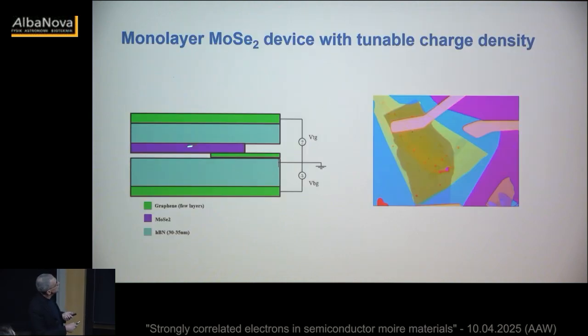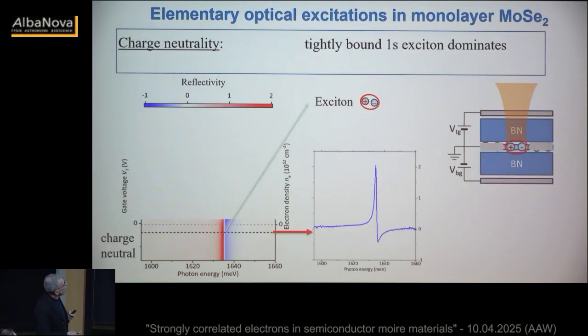This is a simple device where you have MoSe2 sandwiched between hexagonal boron nitride, for which I use the acronym hBN. This is the insulating layer. Then I have a top gate and a bottom gate, which is graphene. I shine light from the top and look at reflection. Graphene allows us to inject carriers. These are the electrostatic gates that I mentioned to you, right? That allows us to control the charge density. They absorb, if it's graphene, 3% of the light each time, so it doesn't reduce the efficiency of the optics. And this is how the device looks with the contacts. So it's all low-tech device fabrication.